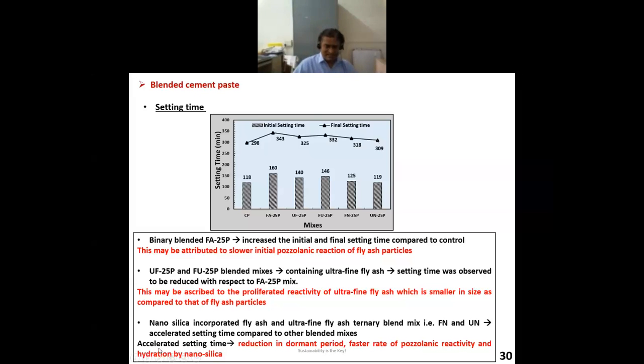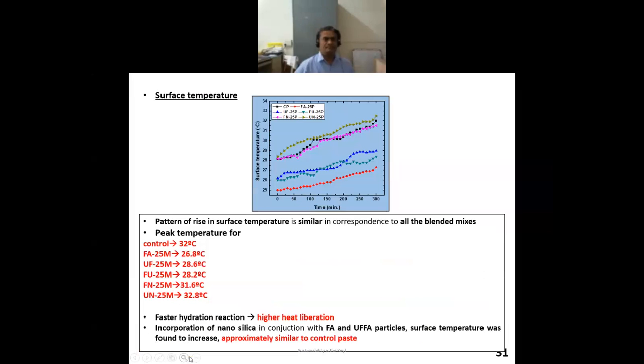So basically, what is the accelerating effect? Reduction in the dormant period, and a faster rate of pozzolanic reactivity and hydration by nanosilica. That is helping me when I add the nanoparticles into the cementitious composite. Then let us see the surface temperature also. These are very interesting results. You can see here the time versus surface temperature. Surface temperature was measured through an infrared gun. Now this is my nanoparticle mix.